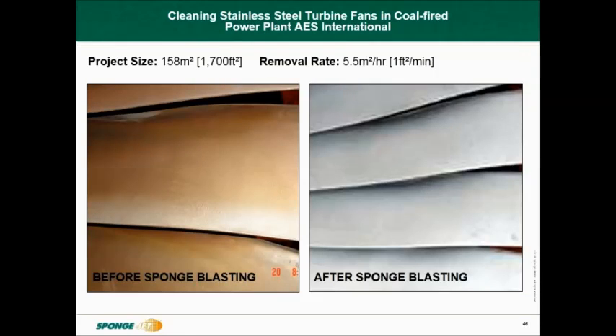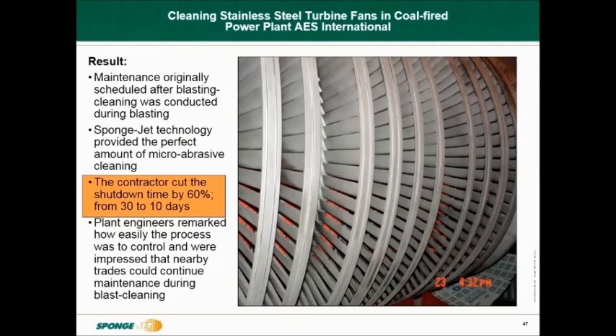This is the first case study that has pointed out the removal rate of 5.5 square metres per hour on a job that involved some 158 square metres. To further those calculations, which I had done, that's 28.72 hours of blast time to blast the 158 square metres. The highlighted section is a great selling point. The contractor cut or reduced the shutdown time by 60%, brought it back from 30 days to 10 days.